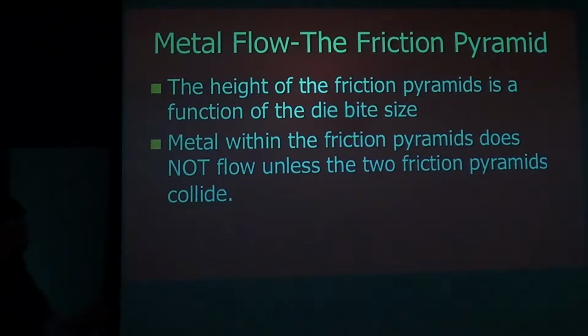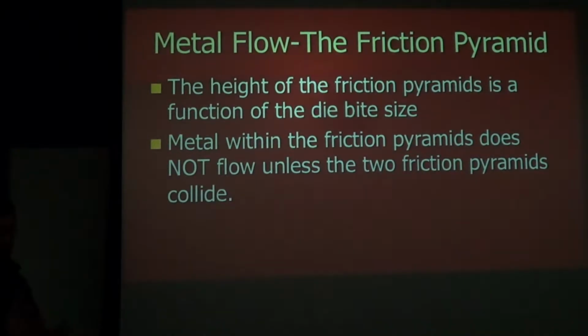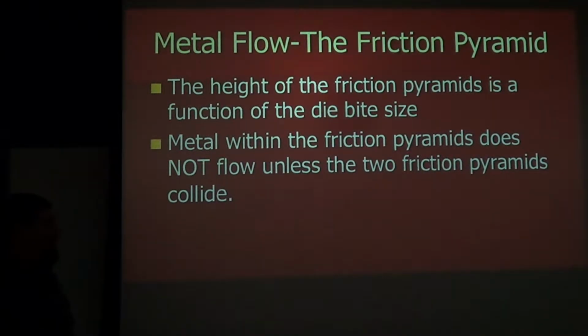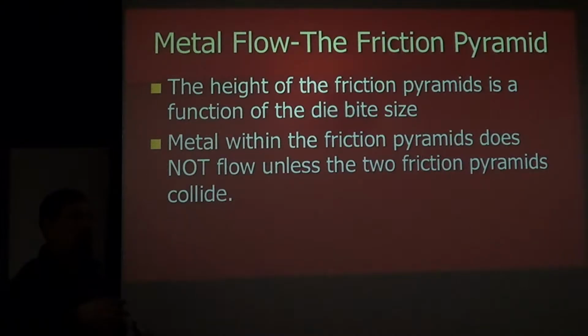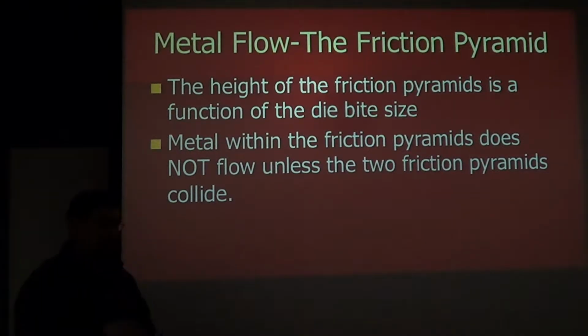So our friction pyramid, if we were going to try to describe it mathematically, we would say that the height of our friction pyramid is a function of how much metal is under the die. I'll show this schematically in a little bit. And that we would also say that metal that's inside our friction pyramid isn't going to move. It's trapped by friction. All that I illustrated in yellow, that's trapped by friction, unless I create a situation in which those two pyramids collide with one another. So that is to say, I have to do enough deformation to get that metal.